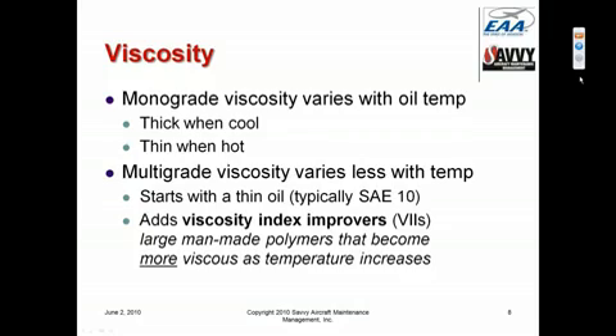So the viscosity of monograde oils varies quite dramatically with oil temperature. Thin when they're hot, thick when they're cool, very, very thick when they're cold. Multigrade oils also have viscosity that varies with oil temperature, but it varies a lot less.